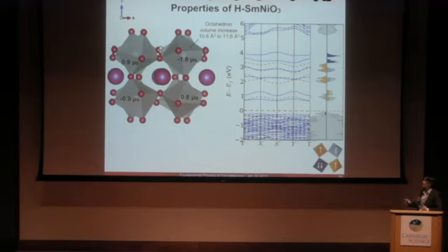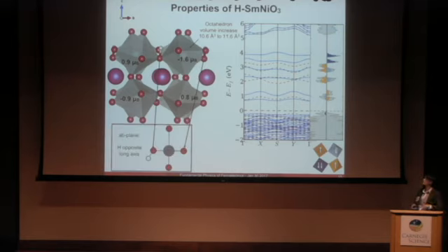I'd also like to point out that the change in electronic structure is remarkably similar to just having an electron and a positive background charge. So if you care just about the electronic structure, the actual position of the interstitials is not so important. As I said, you get a very distorted octahedra due to the hydrogen that now is sitting next to it. So if we're now looking in the AB plane, so imagine looking from above, the hydrogen likes to be opposite to this long bond of this nickel-oxygen octahedra, which is present because of that Jahn-Teller distortion I mentioned earlier.